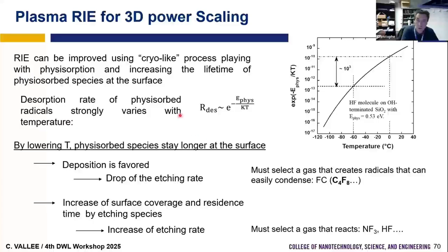And since the desorption is an Arrhenius law, usually when we want to etch, if we want to increase the desorption, so increase the etch rate, we go to high temperature. So when we have a plasma process, usually we say that if we go to low temperature, we favor condensation, so deposition. And if we go to high temperature, we favor etching.